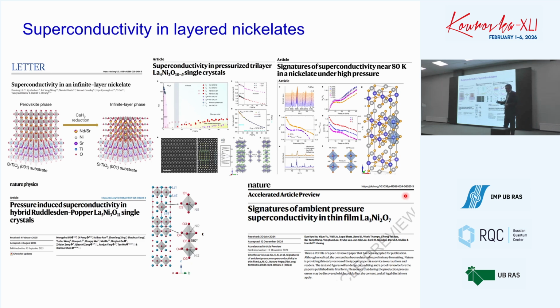This comes from some optimization of the crystal structure and some slight doping, because synthesizing these materials is not that simple. Sometimes introducing some disorder, some doping, even isoelectronic doping, tends to stabilize homogeneous crystal structures, and those materials show really nice superconductivity.